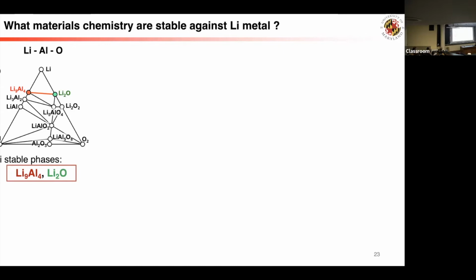So if you use anything like lithium aluminum oxide, what will happen is that if you put it with lithium, you are going to have a reaction going through this line. Eventually it becomes these two, because those are the only two phases that can be stable with lithium. And with computation, we can also evaluate what's stable, and we also evaluate the reaction products.